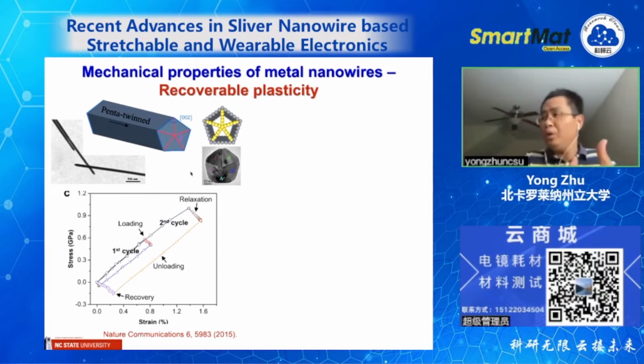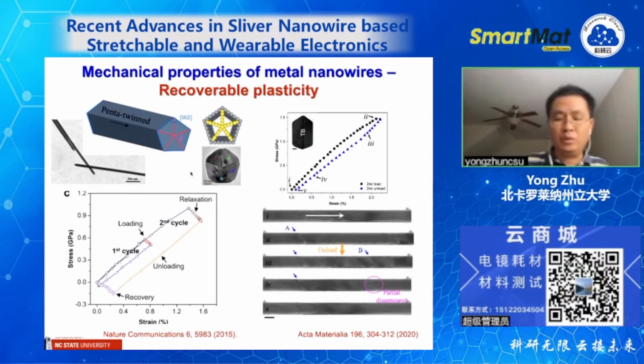The nanomaterial is, as I was talking about, used in some serpentine structures, but also the nanomaterial itself has excellent mechanical properties. It also helps in terms of the recovery in the structure, which is important for stretchable electronics. Here is another case. In this case, you have a single twin boundary along the length, so we can see clearly. This is in situ TEM. We can see the dislocation nucleated, blocked by twin boundaries, and then disappear. If you're interested in the mechanics details, you can refer to these papers.